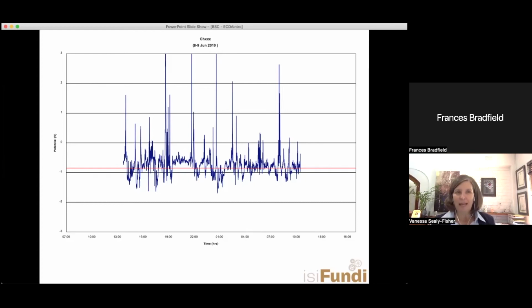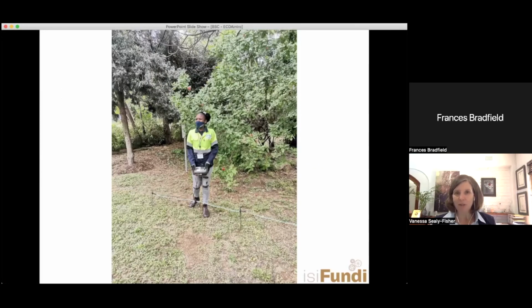Fran, there's of course other surveys that can be used, and I think it's worth not discounting surveys such as the soil resistivity to give us data for our indirect assessment stage. Precisely. I think if you were to think back to the small schematic that we did, in the area that's very high and mountainous and rocky, for example, we would know because we would do our soil resistivity surveys in the beginning, which is how they would know where they need to blast rocks and how they're going to install the pipeline in the first place. We would know what that soil resistivity is, and chances are it's extremely high.